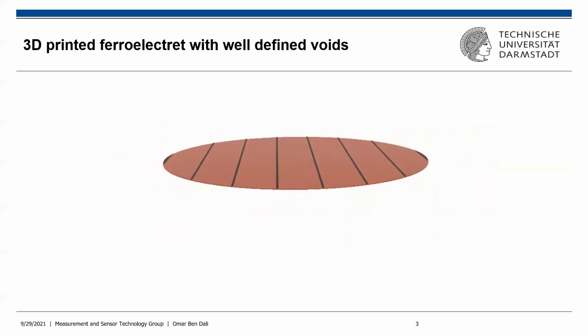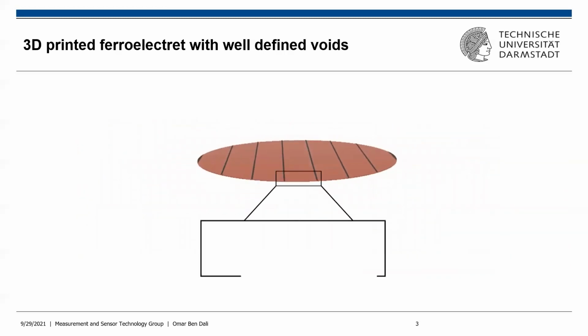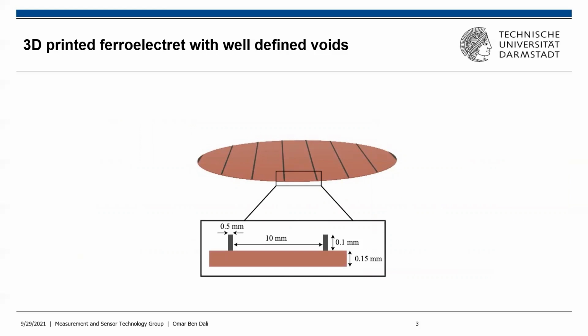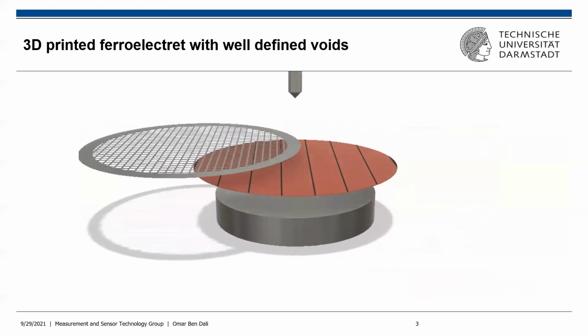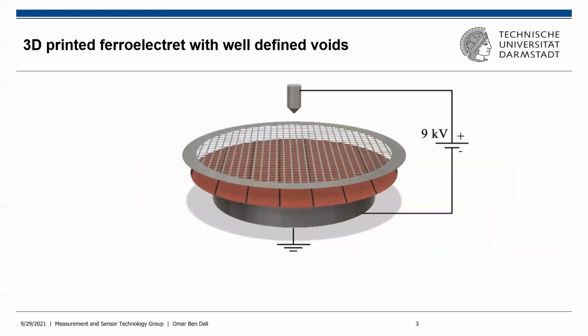The ferroelectret consists of two identical parts. Each part is a circle with ridges on the top, which are at a distance of 10 millimeters from each other. The first step is the electrical charging. For this purpose, we use the corona triode with 9 kilovolt for the positively charged samples or -9 kilovolt for the negatively charged ones. The grid voltage was fixed at 1.5 kilovolt to control the surface electret potentials.